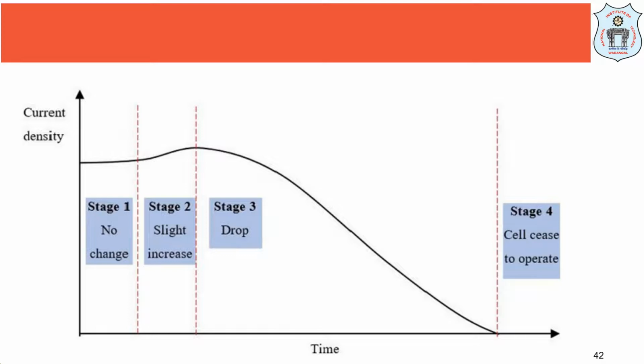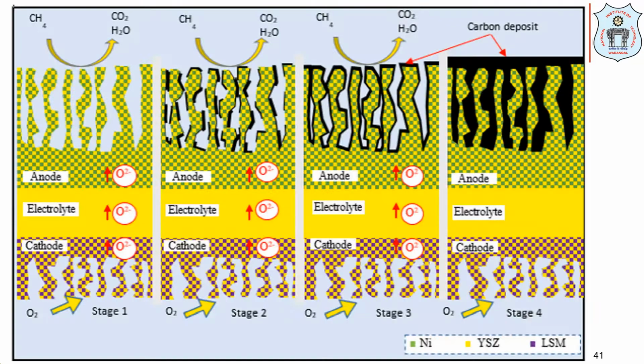The carbon begins to cover the whole surface. So what happens? The clusters of carbon will interconnect to form a layer. It is like a paint coating. The pores have been coated with carbon. So what happened? They act like a barrier layer. However, this carbon deposition is porous, so it will still allow the fuel gases to pass through it and react at the anode surface. So there is a little current density present. Okay. But the reaction kinetics is slowed down here. So there is lower performance.